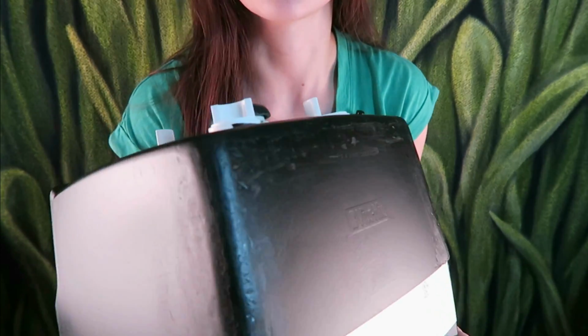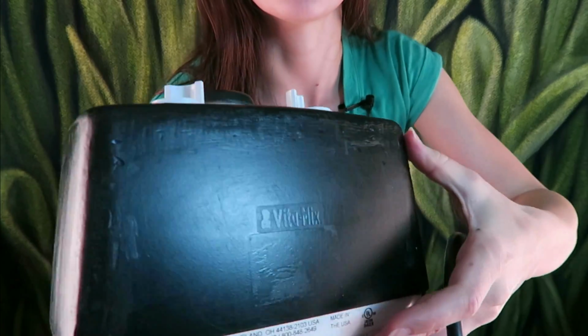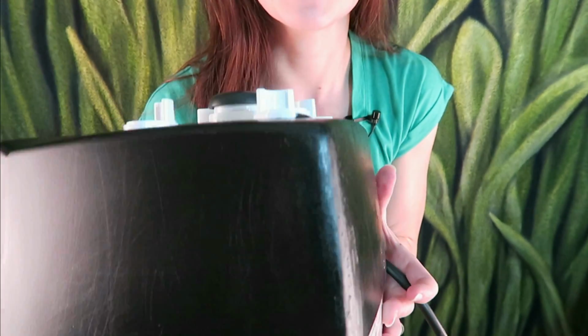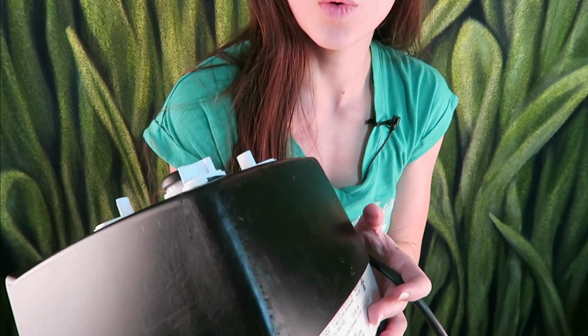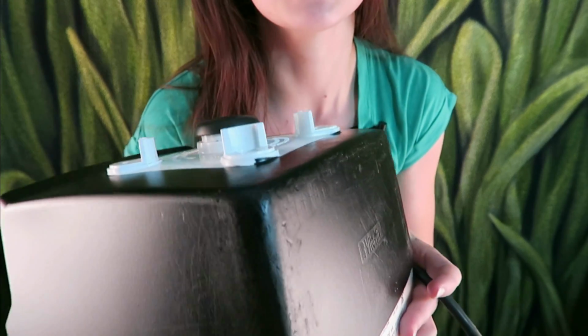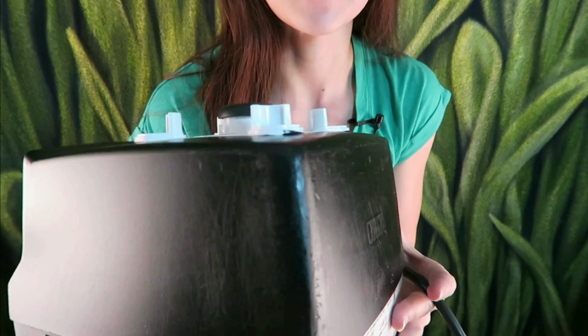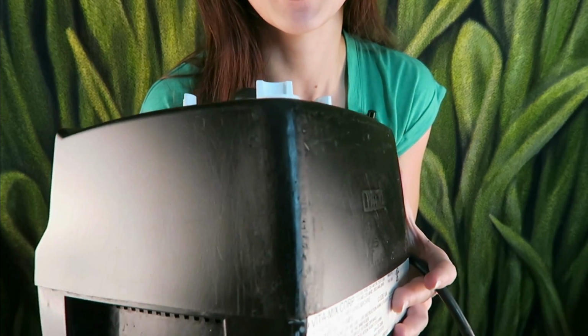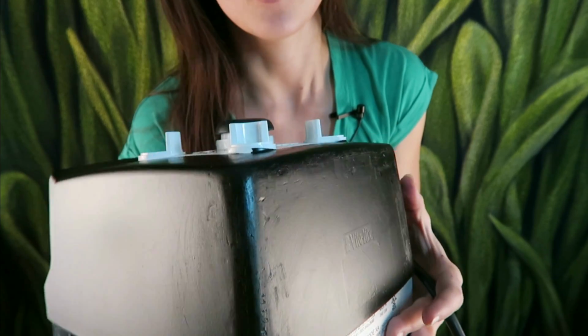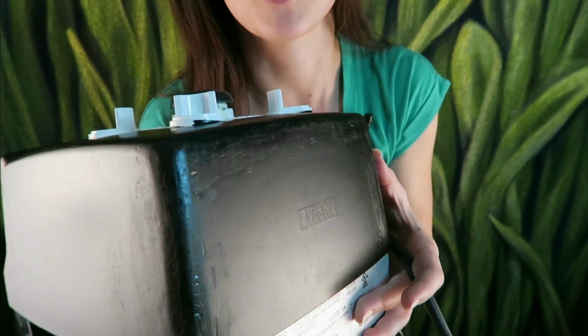Or, you know, functional. You'll see here, obviously, it's not perfect. I definitely didn't get that as smooth as I would have liked, but that's all the time that I have to spend on this, and it was really interesting to work on an actual product for trying out that welder. It's more difficult than I expected to get the welding plastic to mix in with the parent plastic. And as you saw, if you don't actually melt the two plastics together, at least somewhat, then as you sand down, you run into these cracks and gaps and the weld is not actually bonded to the piece.